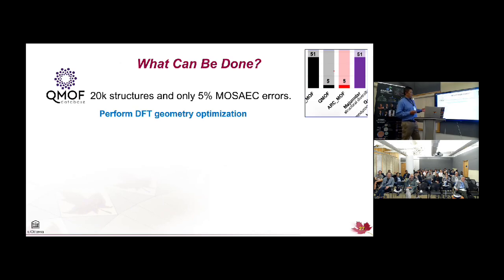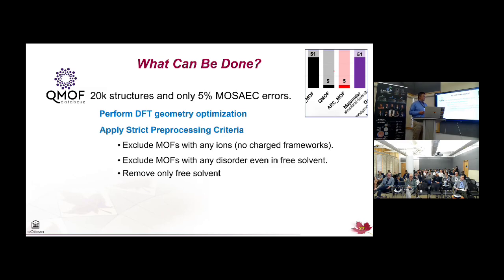So what can be done? Well, if you notice, there are 2 large databases with low errors, around 5%, which is sort of the error window of the method. ARC-MOF is our database, so we used MOSAEC to get rid of the bad structures. But for QMOF, partly what they did was a full DFT geometry optimization, and if the structure didn't blow up, then they kept it. They also used very strict processing criteria. If the paper had anything to do with ions or a charged framework, they would discard it. They wouldn't even try to fix it. Any MOFs with any disorder, even simple disorder, they removed, and they removed only the solvent in the middle of the pore, not anything attached to a metal.